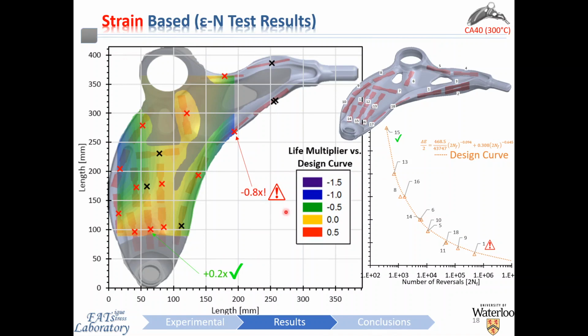Firstly, the contour plot scale here has been exaggerated to highlight any differences throughout the arm, but you can see that in general, when comparing the spatial variation using a strain control approach, the multipliers are much closer to a value of 0, indicating that the design curve more accurately represents the material location, which is a good thing when we're using this for fatigue life prediction. Important to note, however, is that the critical region, which was location 1 in the arm, as indicated in this image here, is still the region with the lowest multiplier or the most non-conservative prediction.